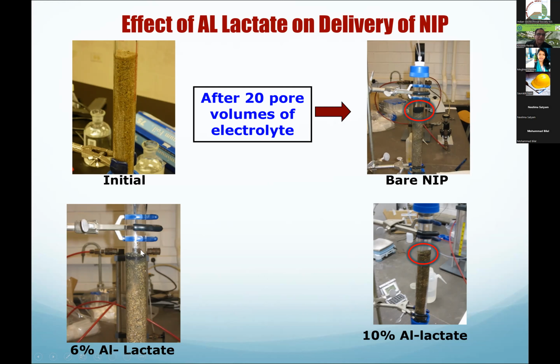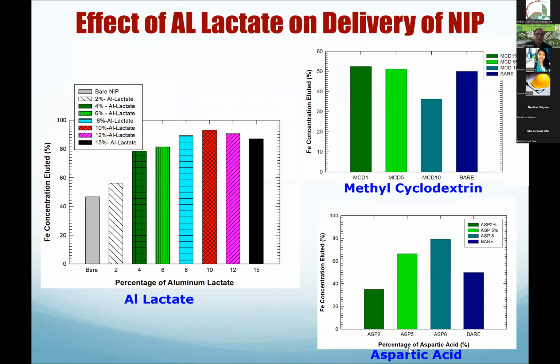You see the dark black stuff with some thickness. That means nothing is moving. So here you see it's less dark, so something is moving. If I increase from 6% aluminum lactate to 10% aluminum lactate, you see this? There's nothing there on the top. All of it has migrated through the sand. So that means, okay, bare NIP, nothing is going to move. But with 6% aluminum lactate, it's going to move a little bit, but not as much. The ideal situation would be something between 6 and 10. Definitely if you use 10, a lot of the nanoiron particles could be transported, and that is evident from analysis of the effluent that comes out.